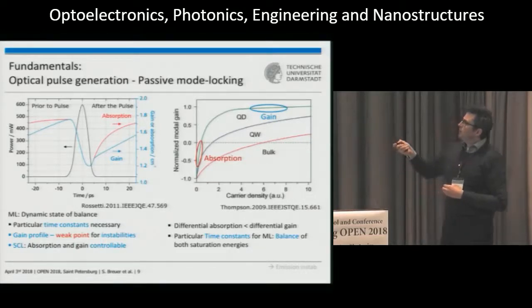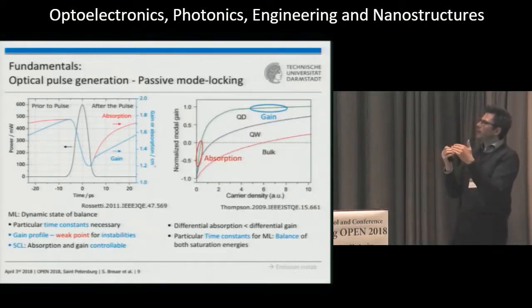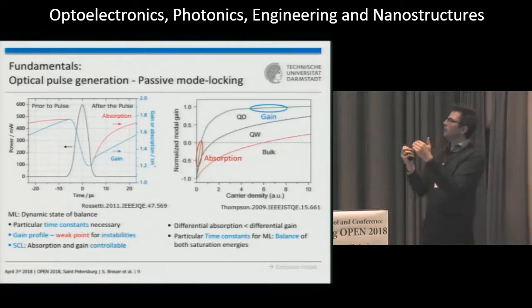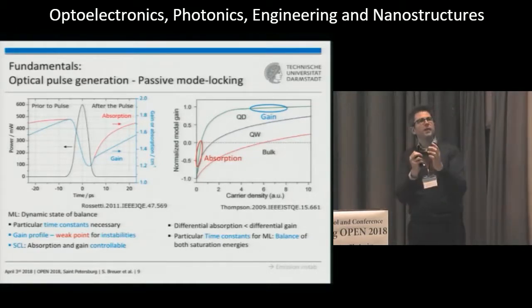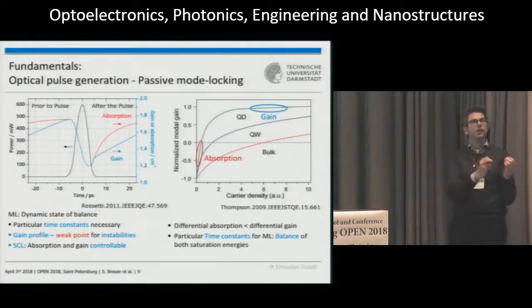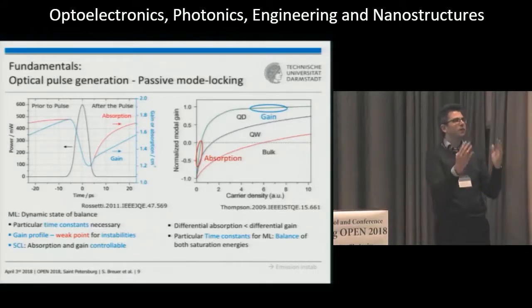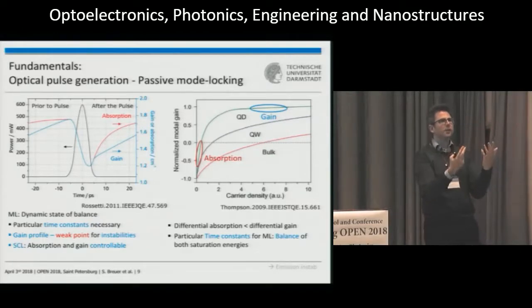And of course, you can see if these time constants do not fit properly, this gain profile can be subject to different disturbances, like, for example, leading edge or trailing edge instability. As soon as there are leading or trailing edge instabilities, you find that the pulses deviate in position, and this immediately translates to a change in the stability of the mode comb.